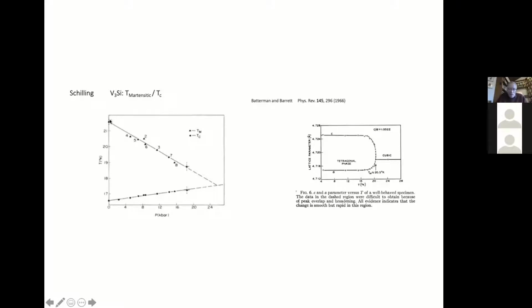And this is a picture here, this data from Jim Schilling, where you have this so-called martensitic transformation, this cubic to tetragonal transformation, as a function of pressure here. And this is TC, in the crystal he had a little below 17, slowly going up, coming out to this point here. And this over here on the right is what the lattice parameter looks like as a function of cooling down in temperature at ambient pressure between these 2 points. You see this lattice parameter changing here. And then coming to TC, below TC, you actually don't get much change.